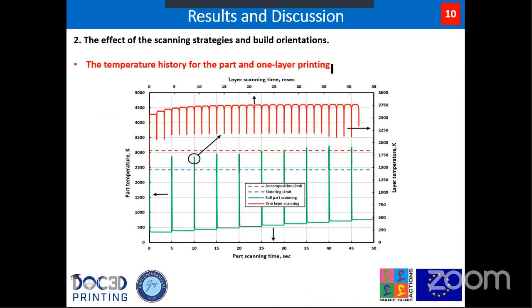And we obtained the temperature history during the whole building process, where you can see that the green line presents the temperature history for the whole scanning process. Each line of this green line, if we expand it, we will obtain the scanning history for one layer. Our part has 10 layers. So if we expand this line, we can obtain the scanning for one layer.